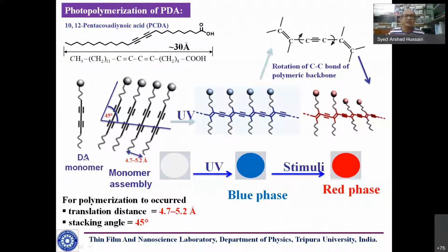So polydiacetylene, mainly this is a diacetylene monomer. When they align and organize in a specific arrangement, say the angle between this one and this is of the order of 45 degrees and the distance is of the order of this, then upon exposure to UV, polymerization occurs. Okay, so this is the polymerization. Then again, if you expose it with further UV or temperature or other stimuli, twisting occurs here, and orientation changes.